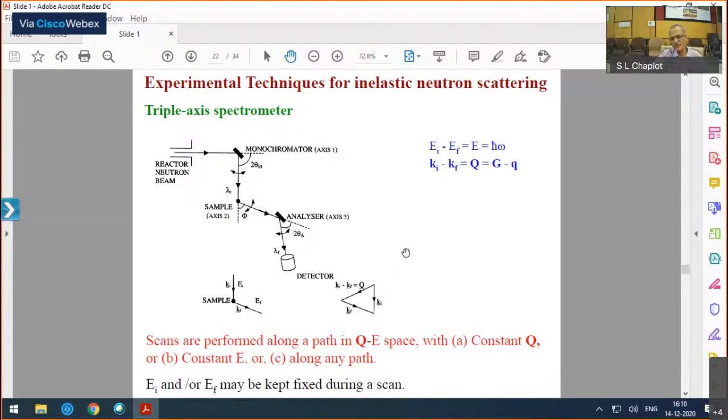And then if you have a multiple scattering process, my signal may be corrupted. The corresponding spectrum that I may get will be a combination of the two. So often we choose sample thicknesses which give, say, around 10% scattering, and we can calculate it because we know the scattering cross sections, 4 pi b square, and we also know the absorption cross section and so on.